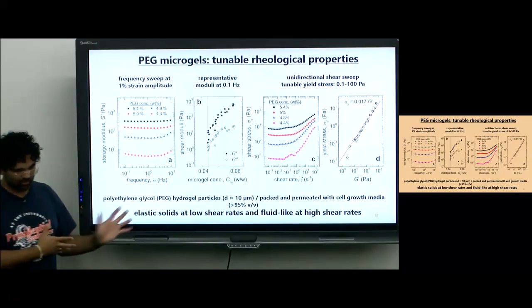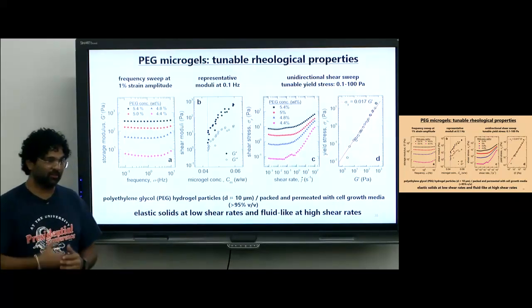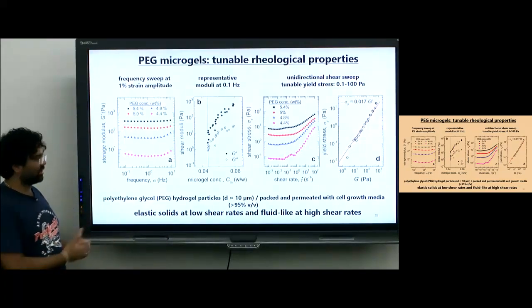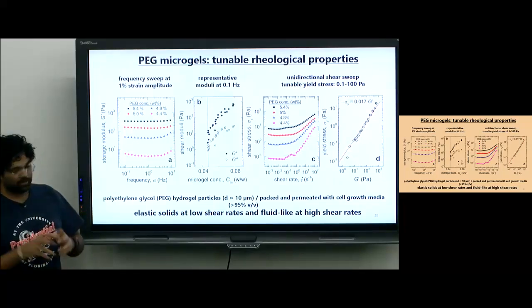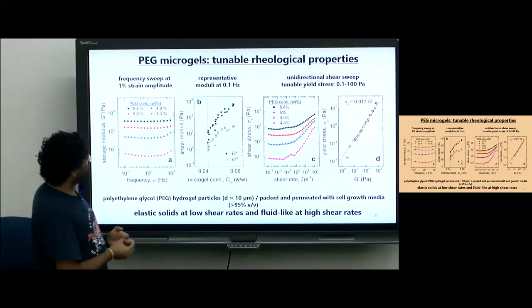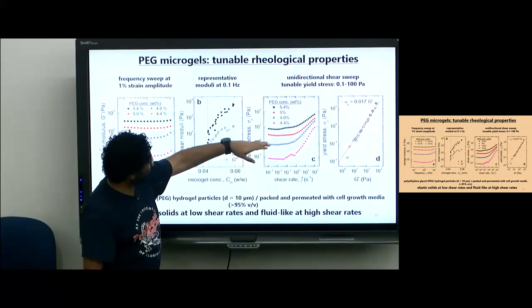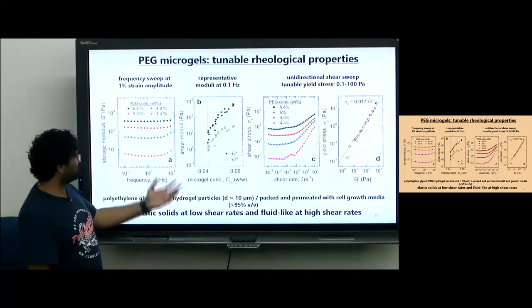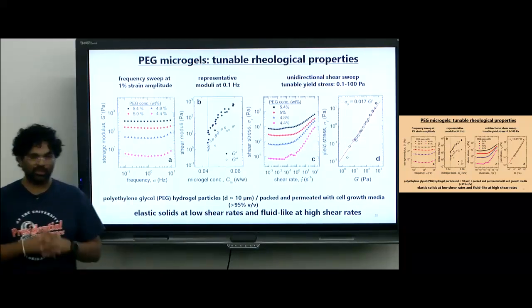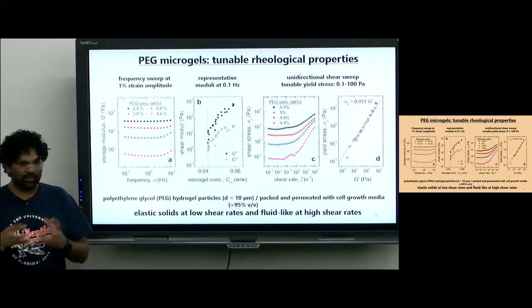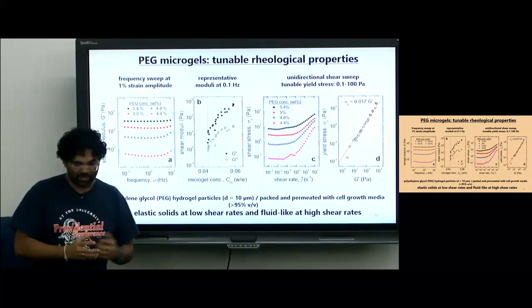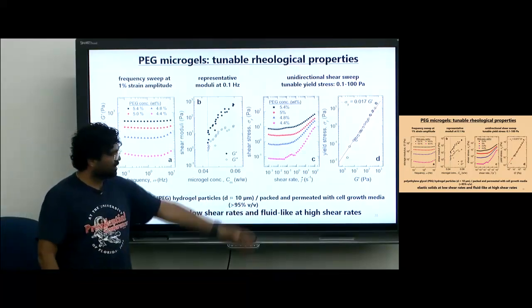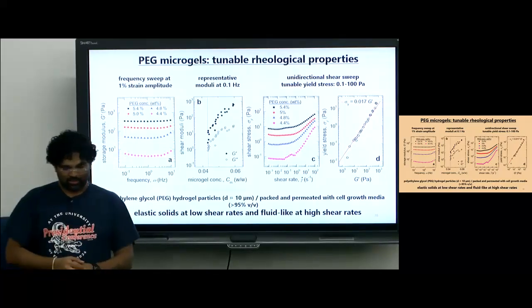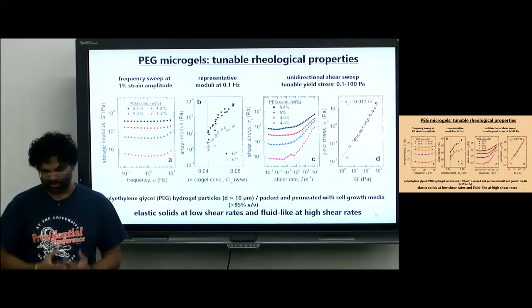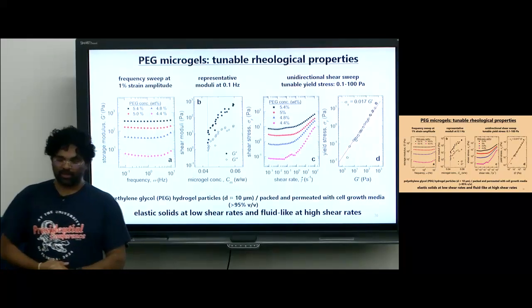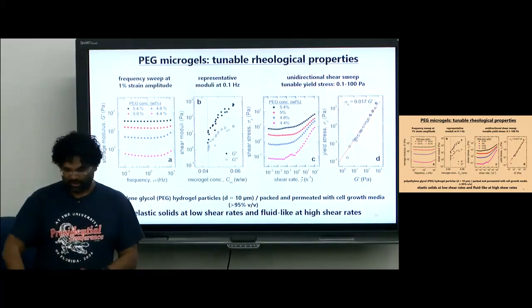We were talking about rheology, so we characterize these materials because we synthesize them in the lab. We need to understand what the modulus is, what the yield stress is. So we did a whole bunch of shear rheology on these polyethylene glycol microgels, and we found that at about 4.8 to 5%, where you have a yield stress of say a couple of pascals, is a sweet spot to be able to print these cell suspensions and little tissue models. Again, these are elastic solids at low shear rates, but they behave fluid-like at high shear rates. So just to show that when we make something like this, we need to characterize and understand how we can precisely print what we want to print.